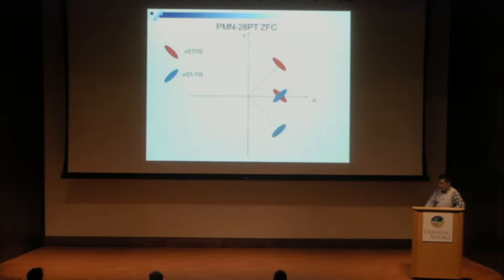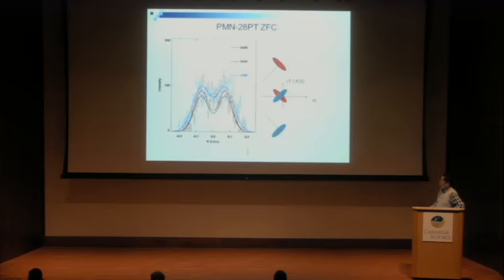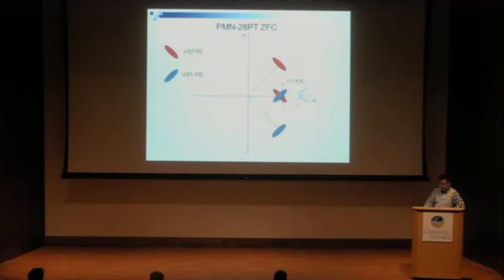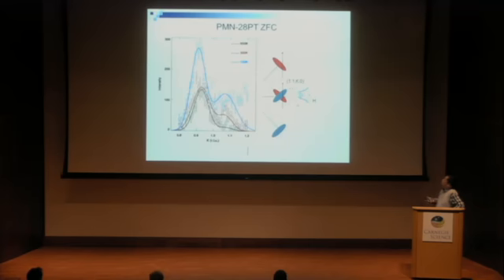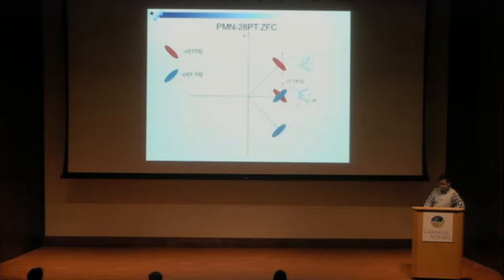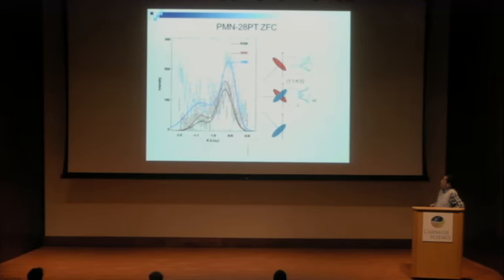To better understand the data, we also did a linear scan, a K-scan at h equal to 1.1, which crosses the diffuse scattering and avoids the strong Bragg peak. As we expected, in zero field cool, the contributions from the red and blue wings should be equal or similar, and we see a symmetric two-peak pattern here. In this scan direction, the left peak always comes from the red wing, and the right peak always comes from the blue wing. Near the 110 Bragg peak, the peak from the red wing is much stronger, but there is still some intensity from the blue wing. And near the 1-10 Bragg peak, the situation is similar, but the opposite way.